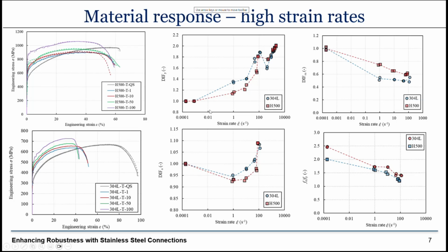And from the obtained results, we were able to plot the dynamic increase factor, so basically normalizing the relevant material properties by the relevant properties under static or quasi-static loading conditions. We can see that in all cases, the nominal yield stress increases significantly with increasing strain rate. It can increase up to about 1.8 times. I should also point out that up to the strain rate of 100, so 10,000% per second, tests were conducted in a conventional tensile machine, whereas for higher strain rate, a split Hopkinson bar test was used to find the material properties in compression, and that's why we obtained the effect on nominal yield stress, but not on ultimate stress, since under compression there is no ultimate stress.